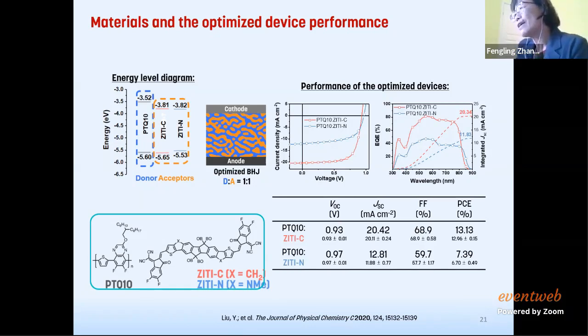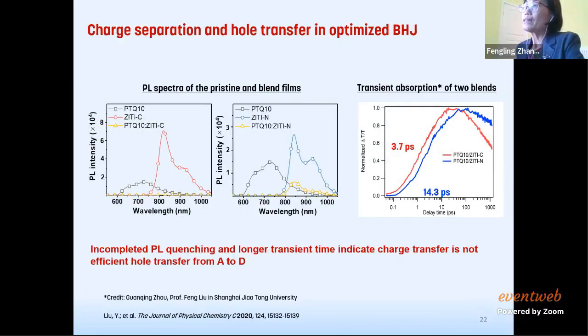So then we try to understand how it works. It's hard to understand how, with such negative driving force, we still get such good photocurrent and fill factor. So we check the photoluminescence to see whether the charge transfer is efficient. Then we can see a big difference between the two acceptors. For the acceptor with the small driving force, the PL quenching is better than for this ZITI-N. For ZITI-N, we can see the yellow part. It's very obvious. So indeed, for the system with the negative driving force, the PL quenching is not complete, meaning the charge transfer is not very efficient. We also check the lifetime of the exciton. The transient absorption shows that for the negative driving force, we have a longer exciton lifetime, meaning they do not separate easily.